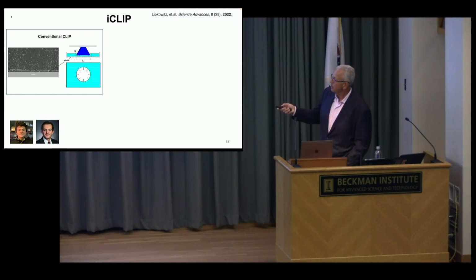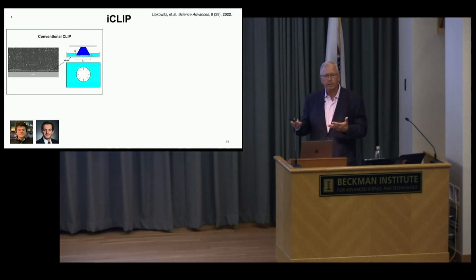CLIP, as I showed you, is drawing liquid into the gap. And the liquid, as it's shown in cartoon form here, is coming in from the periphery of the part as we print this cone. Top-down view, you see all the liquid coming in underneath it. This is still a mass transport limited process. The chemistry will go way faster, but this gap is between 20 and 80 microns depending on how you run the process.